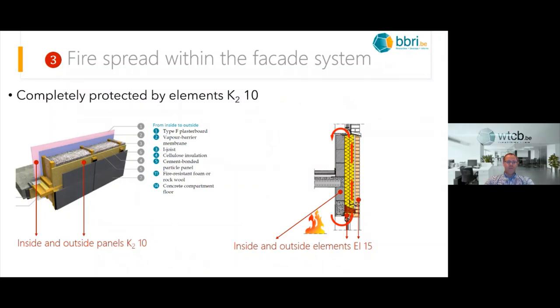If you have a wooden structure, then you have to put panels inside and outside to protect the insulation from a fire from the outside and from a fire from the inside. So it's very important to take this into account. Or with a more traditional wall with brickwork, the fire resistance of the brickwork can also be used to protect the insulation, but you have to pay special attention to the junction between the masonry and the windows so that the fire can't get into the cavity at that place. So that's very important.